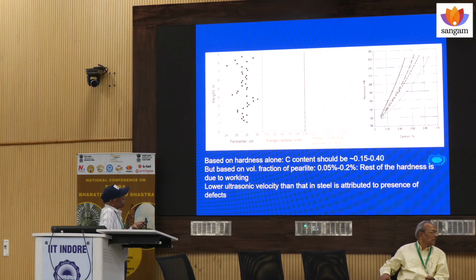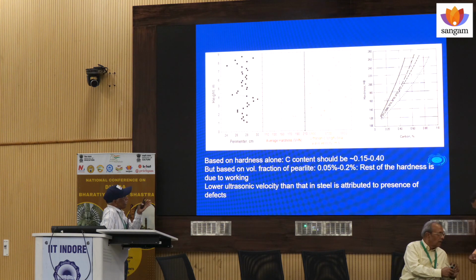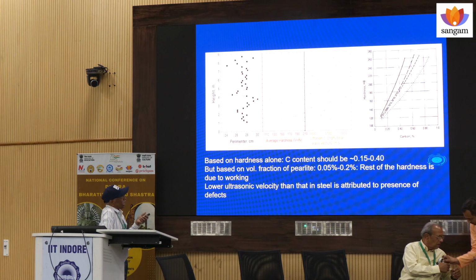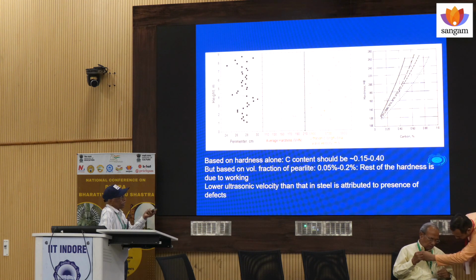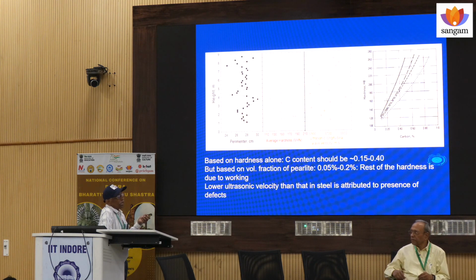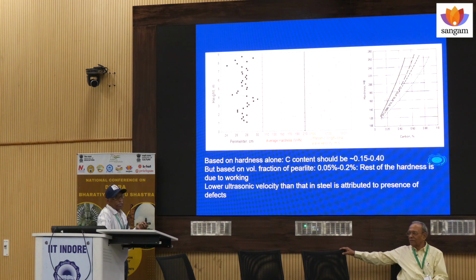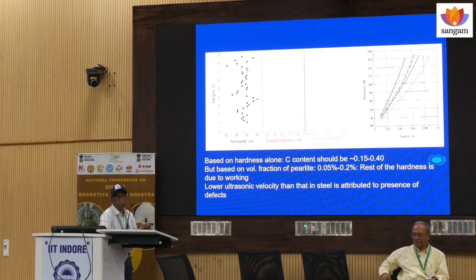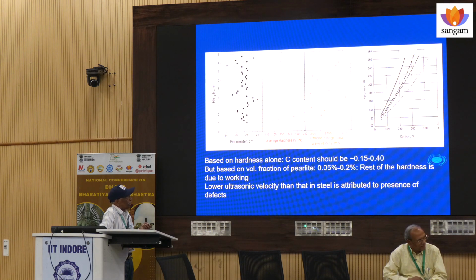And if you see the hardness variation and the composition of the carbon which we have taken based on the ferrite pearlite percentages, and the expected hardness taking into account certain heat treatment conditions, the hardness of the pillar is more than you can account for from the carbon content inferred from the ferrite pearlite compositions. So what we believe is that it is in the worked condition. That's why the hardness is more than what is expected in an annealed ferrite pearlite condition. So that is another piece of information we could obtain.